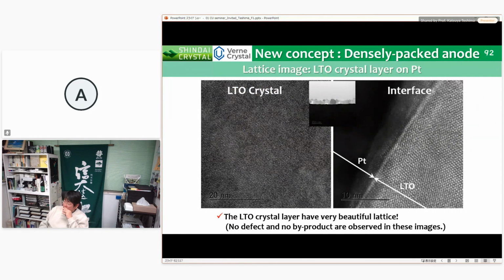These are the lattice images of the LTO crystal layer on platinum surfaces. The LTO crystal layer has very beautiful lattice, as shown in these pictures. No defect and no byproducts are observed in these lattice images.